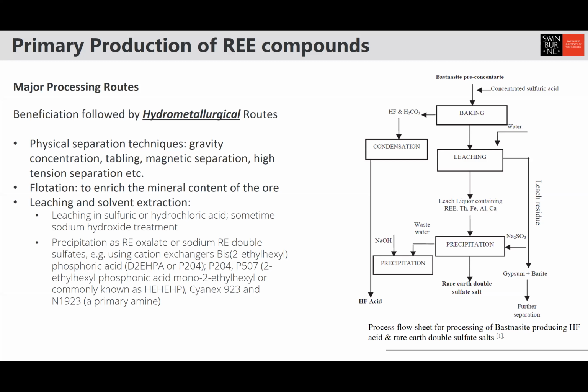After we do that, we then do the followed by precipitation or solvent extraction. The one that we have here on the right is an example of processing bastnasite REE ores. In here, first we have bastnasite pre-concentrate. So we do the physical beneficiation and flotation process first, and then we use a leaching process to get a leach liquor that contains thorium, iron, aluminum, calcium, in addition to the rare earth elements.